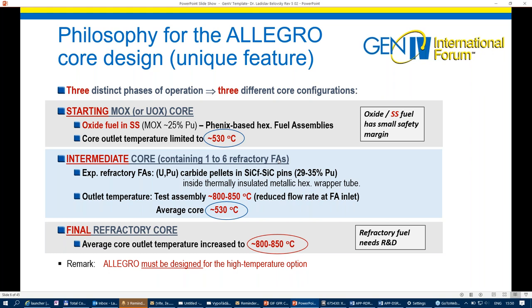And these test fuel assemblies will be able to reach the target temperatures, the target coolant temperatures at the outlet being in range of roughly 800 degrees C, thanks to reduced flow rate going through these test fuel assemblies. After mixing with the coolant from the driver core fuel assemblies, the average core outlet temperature of the primary helium will be again limited to roughly 530 degrees C.